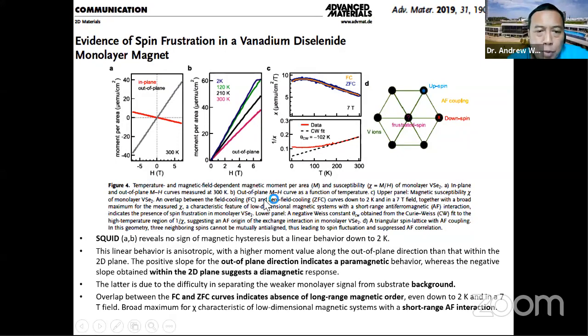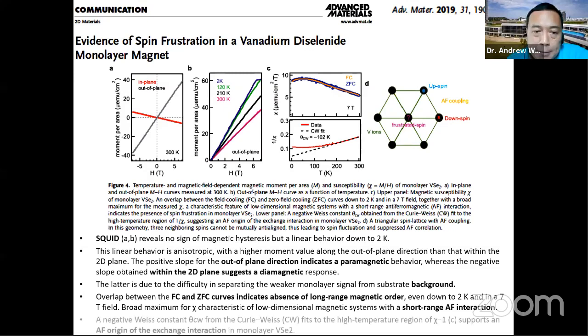And the broad maximum in the susceptibility is characteristic of a low-dimensional magnetic system with short-range anti-ferromagnetic interaction. And the negative Weiss constant in the 1/chi curve also supports the anti-ferromagnetic origin of the exchange interaction. But this magnetism is very small.